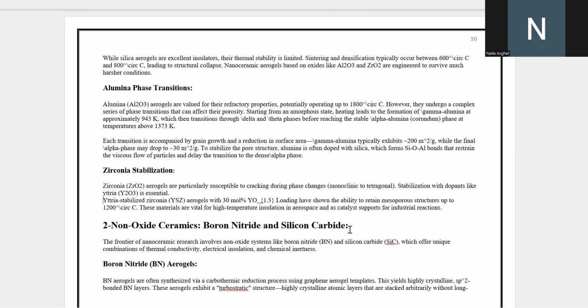And the second type is zirconia aerogel, the strong but brittle one. Their superpower is their excellent insulation and chemical stability at high heat. The catch is that it has a major weakness. When heated or cooled, it undergoes a sudden phase change that makes it expand or shrink slightly. This creates enormous stress, causing it to crack and turn to powder. To fix this problem, it is always stabilized by mixing in another metal oxide like yttria.